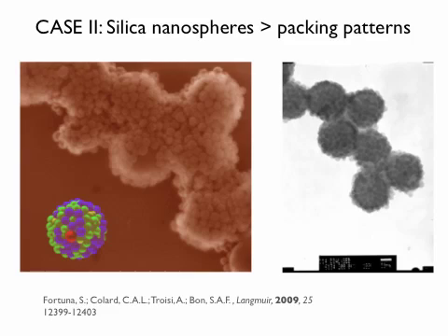So you have particle nucleation versus particle growth. They're related to each other. So you get monodisperse spheres if the particle nucleation period is short relative to the total period. But if you want to make small spheres, your growth period is really short, otherwise they're big. So it's difficult to have a relatively short nucleation period, which means there's a dispersity over your particle size, which is generically 10, 15% or higher if particles become really small. So that's a big problem.